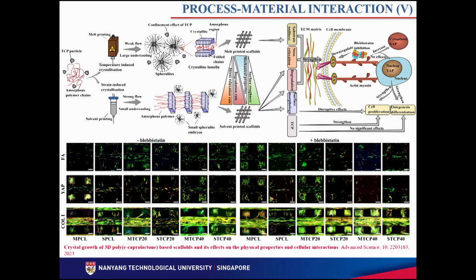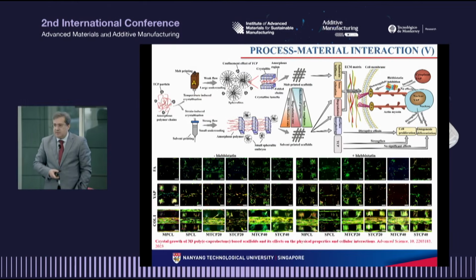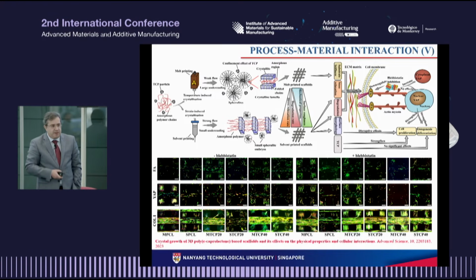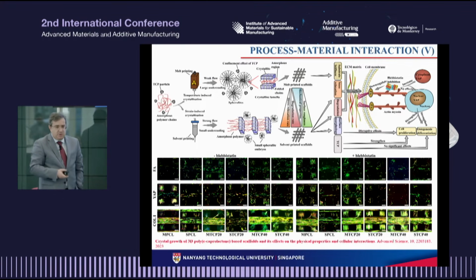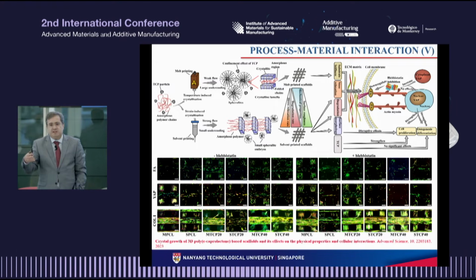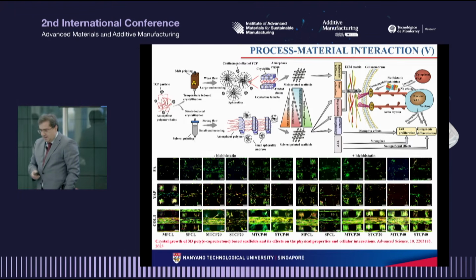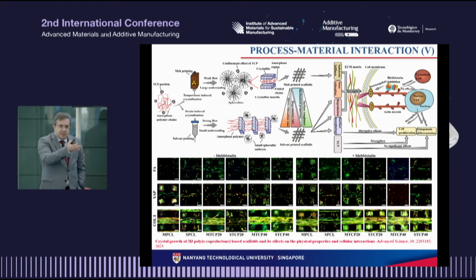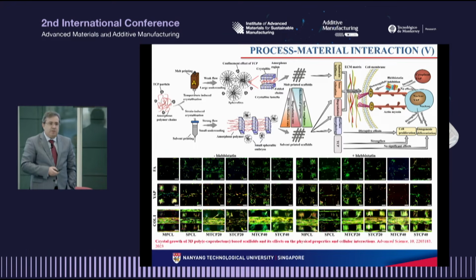Another example about how we can design performance by controlling the microstructure is again related to bone scaffolds. So in this case, we produced PCL-TCP, a composite polymer-ceramic material, using two different fabrication routes. In one case, we used a melt printing process characterized by a temperature-induced crystallization, leading to the formation of large and interconnected spherulitic structures. And the second was a solvent printing approach.